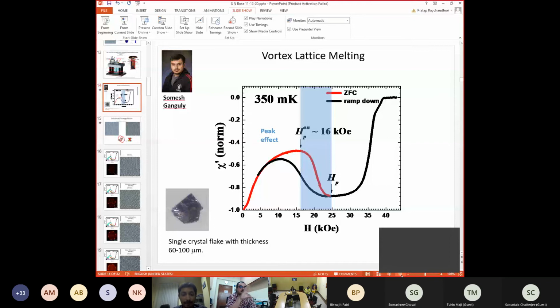Now you will ask why this hysteresis. This hysteresis is because this is a first order phase transition. This has been seen in susceptibility and magnetization, and studied by many people for many years, including Grover, Satyajit, Ravi Kumar, and so on. But in real space, we have also done this experiment through imaging, and it's very interesting because this is related to superheating and supercooling of the phases, and you can actually get superheated and supercooled vortex lattice phases.